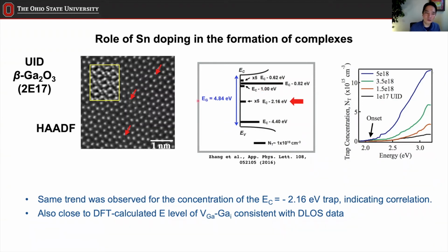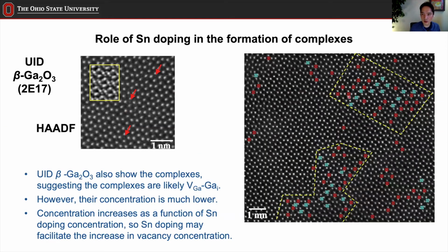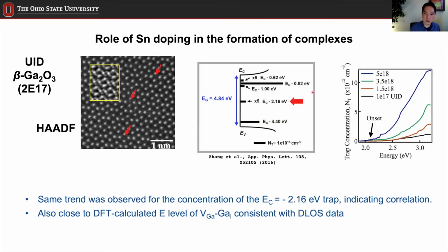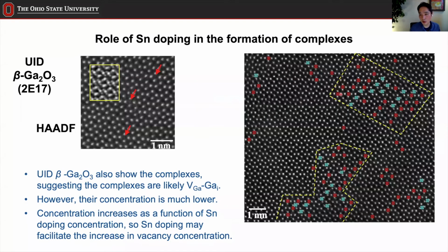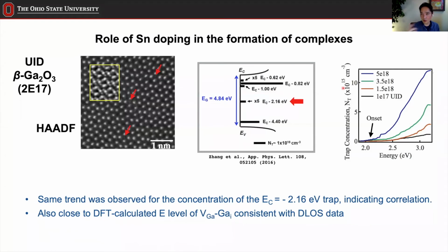And what they saw was when the tin doping concentration was increased, this particular one has changed its concentration. In fact, this was the only one that showed the change in concentration. So same trend was shown then, right? So the tin doping concentration increased the number density of the complexes here, and also this one had the same behavior. So we can make the correlation. So it's very likely that this particular trap state is correlated to the formation of the defect complexes that we observed here. So that's how we made the correlation.